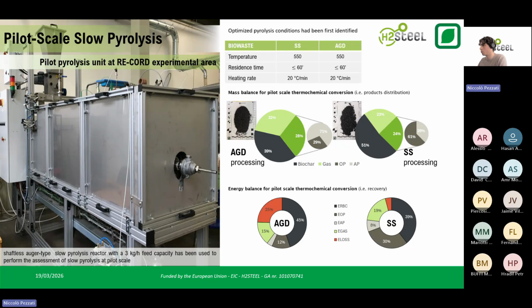Apart from, of course, assessing the mass balance of the process, we have also assessed the energy balance of the process. And as you can see here, we are able to recover 45% of the energy initially comprised in the feedstock of the agricultural digestate into the raw biochar, which is produced from that particular biowaste, whereas in the case of processing the sewage sludge, 39% of the energy which is comprised in the sludge eventually ends up in the raw biochar.